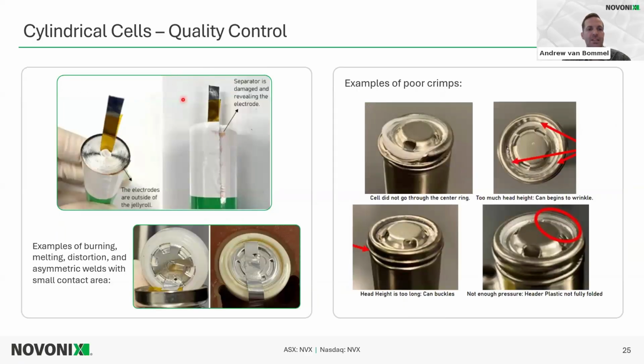So here are some issues that can arise during production of the cylindrical cells. In this case, we mentioned that the separator has to have a 1 millimeter overhang from the anode. In this case, those electrodes are protruding outside the jelly roll, so we have to check the winder to see if everything's proper here to fix this. In this case, the separator is damaged, and this reveals the electrode. So we have to ensure that there's enough wraps and there's no damage of the separator revealing the electrode.